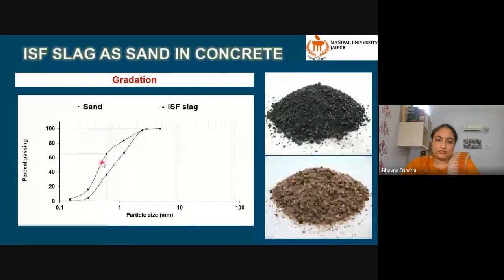This sieve is 600 micron, that is 0.6 mm. Natural sand has a portion of more than 60% passing. However, ISF slag has less than 40% material passing the 0.6 mm sieve, which clearly says that ISF slag is coarser. However, there is no problem. We can deal with it because this matches very closely with natural sand.